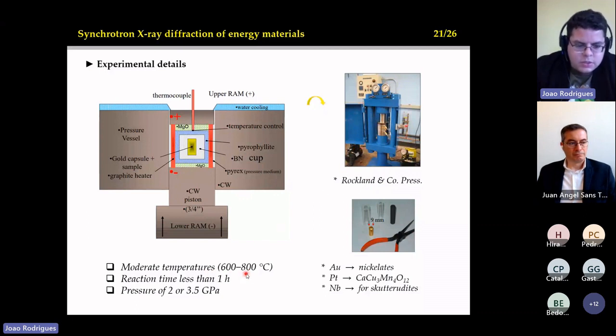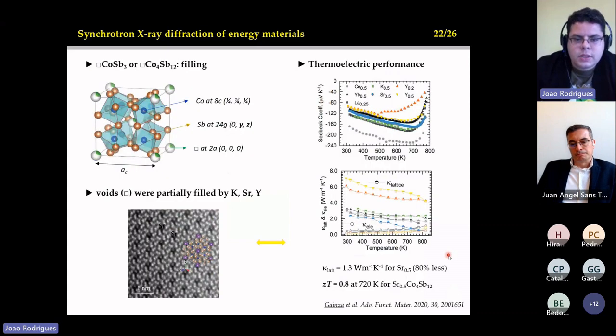These materials were synthesized under pressure using the so-called piston cylinder press, at moderate temperatures and pressures of 2 and 3.5 GPa. And then we discovered in Madrid that for these skutterudites, you need to use niobium capsules, which are cheaper than gold and platinum. Like this, you can save money, and you can also produce these new compounds on a large scale.